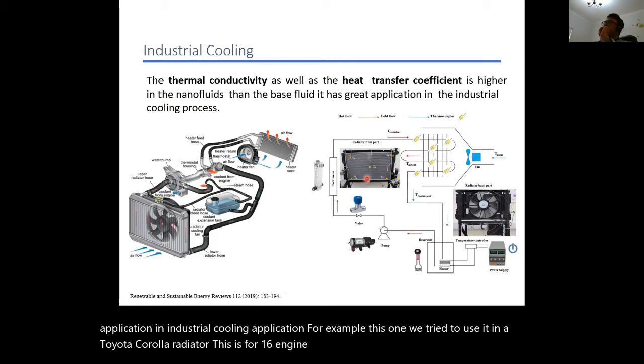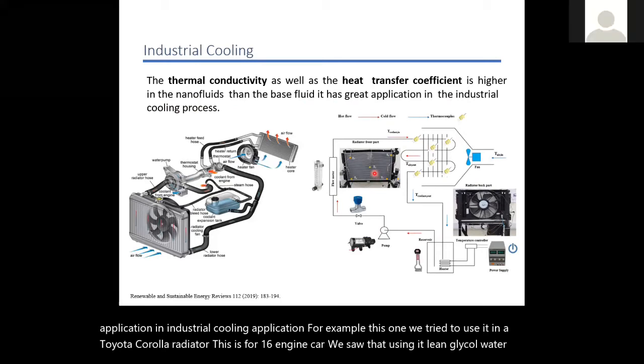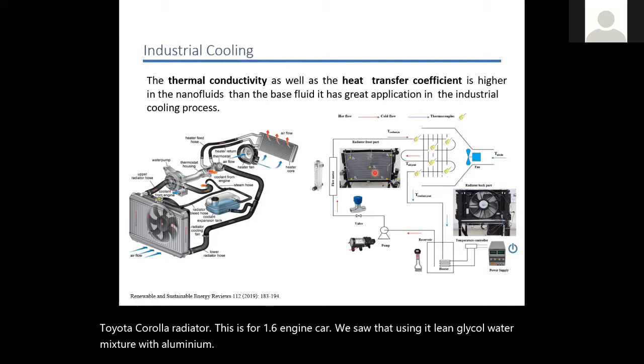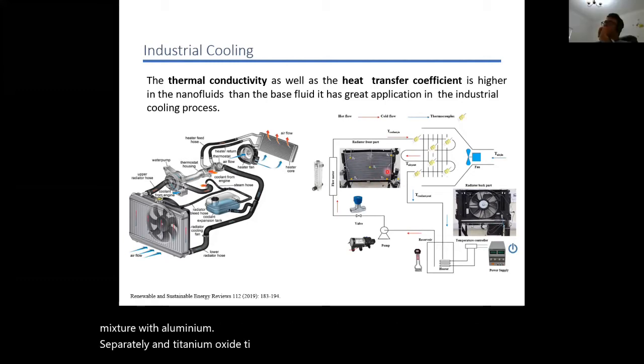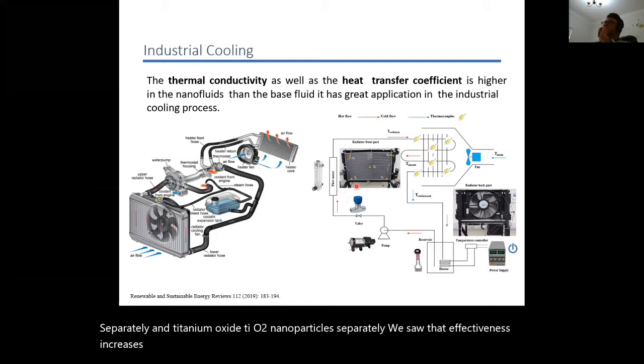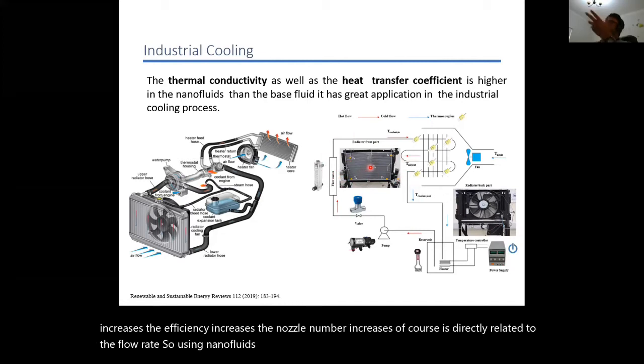We saw that using ethylene glycol water mixture with aluminum and titanium oxide TiO2 nanoparticles separately, the effectiveness increases, the efficiency increases, the Nusselt number increases. Of course, it's directly related to the flow rate. So using nanofluids in such systems could enhance the overall performance, as well as result in reducing the size of these heat exchangers.